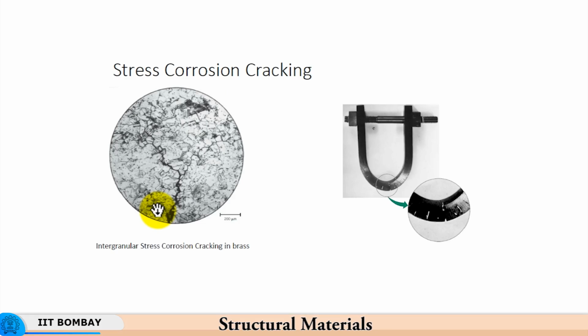So, if there is residual stress, it will get relieved by virtue of the generation of new surfaces due to corrosion. In brass, for example, you have stress corrosion cracking taking place because this region was under high stress, and the corrosive element, let us say the corrosive electrolyte, found these highly stressed, high energy regions much more amenable for a corrosive attack.